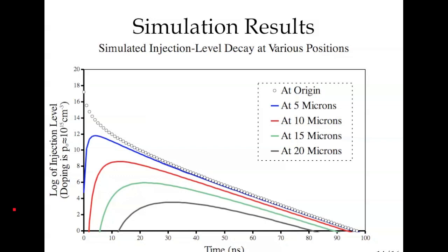So what that suggests is that we want detectors, if we really want high dynamic range, if that's the important parameter, we want detectors with smaller collection volumes or smaller active areas. Since they'll sample much more approximately this type of result, rather than an average effect of all of the results. If I were to average those signals, I would end up with a signal that represented a lower injection level. So it's basically the idea that I'm just looking for local homogeneity rather than homogeneity over a larger scale.